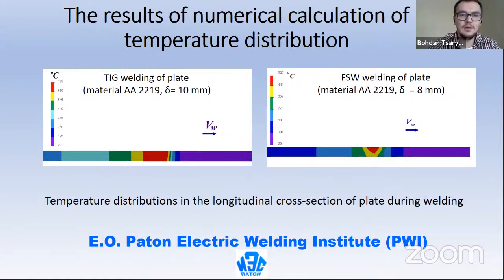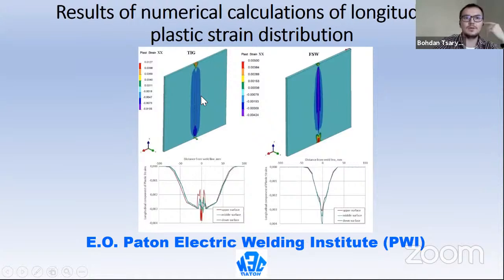After modeling, we have diagrams of temperature for aluminum alloy, for TIG welding and FSW welding. Here we can see that the temperature in TIG welding is much greater than that for FSW welding, and also the area of the weld of the highest temperature is much greater than for friction stir welding. Here are the results of numerical calculation of longitudinal plastic strain distributions.